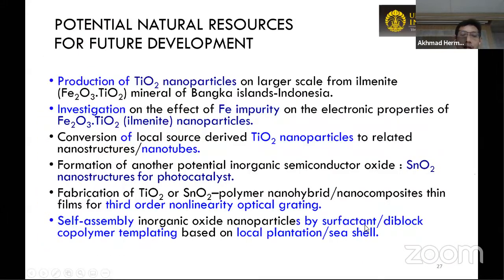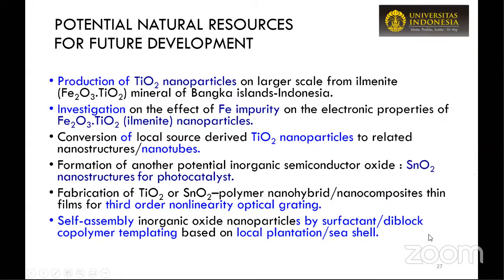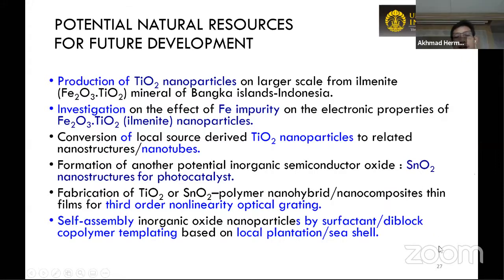I think this is the last slide that I present today. It is not a conclusion, but I just want to give you, and at least for myself, that we have this kind of potential to be developed further. So we can produce TiO2 nanoparticles on an even larger scale from ilmenite, because in the previous work we could only get a small amount of TiO2 nanoparticles from the ilmenite. If we can scale up the line of production, then we can provide TiO2 nanoparticles with uniform distribution in particle size.